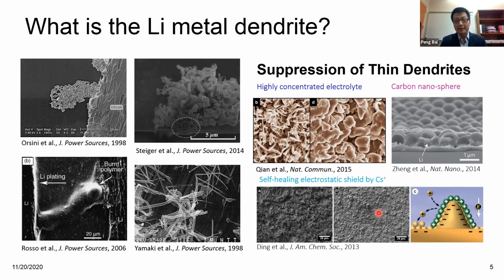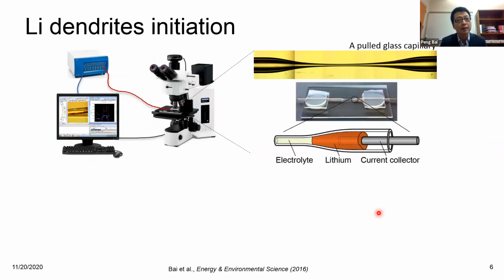But the problem is that no matter how you do this, as we already discovered, if you increase the current density for charging your battery, you will always see penetration. That's very unfortunate. But imagine that in the future, we will have higher energy batteries. At the same time, we still want to charge them relatively fast. We don't want to compromise and wait a longer time. That means you will have to increase your charging current density. So eventually, penetration can still happen. That's why it is very important that we start to look at the penetration process.